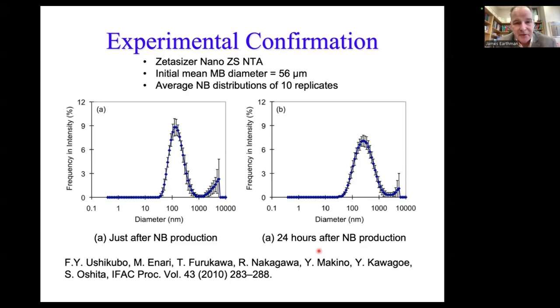And they measured the distribution of nanobubbles produced by a large diverse microbubble distribution. So they would start out making microbubbles. They wait for the microbubbles to shrink, and then they would make these measurements of the nanobubbles. Okay, and these are the average of 10 replicates for them. The mean microbubble diameter they start with was 56 micrometers, so even above the 50 micrometers in size, but anything larger than 50 micrometers won't shrink, so it won't form a nanobubble, according to our theory. And if you look at the maximum size here, this is just after production, it maxed out right about 1,000 nanometers. A little bit later, 24 hours later, you can see, it's right around 1,100, where you would expect from our theory. So that was pretty good confirmation.